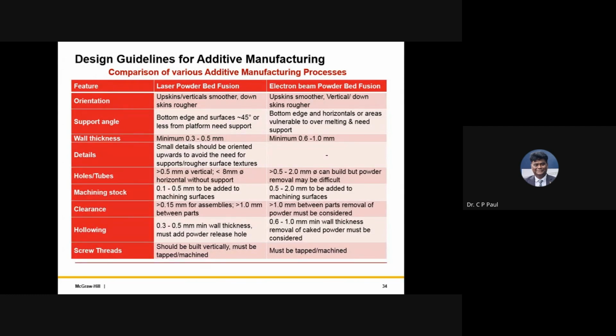And similarly, if we talk of clearance, we have to keep 150 microns clearance in assemblies and 1 millimeter in parts, while more than 1 millimeter in the parts to remove the powder particles. So if you compare the electron beam powder bed fusion machine with the laser powder bed fusion machine, then the laser powder bed fusion machine scores many positive points. But in terms of fabrication time, the electron beam powder bed fusion machine takes us to the next level.